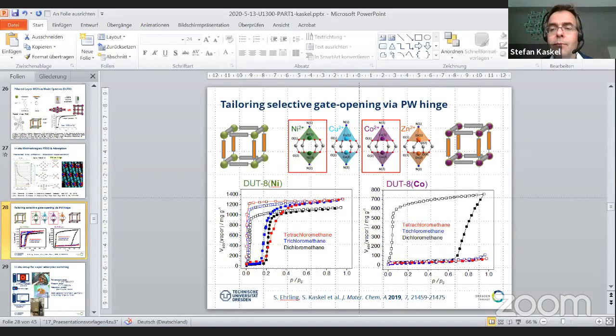Thank you. Then again, there's a question from Angel Hujati. Can we observe a negative gas adsorption in gravimetric measurements at ambient conditions? Yes. For example, for butane, you can measure butane adsorption in a microbalance, and you can also see the negative gas adsorption there. There's a step in the weight, in the gas uptake in the weight.